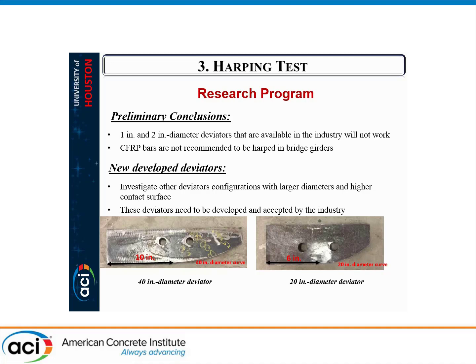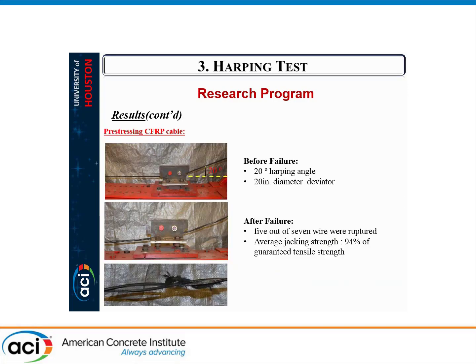So with the idea of increasing the contact surface and reducing the contact pressure, we developed two deviators. One of them has a 6-inch straight portion and a 20-inch diameter of the curve, and the other one had a 10-inch straight portion and a 40-inch diameter of the curve. And the result this time has improved a lot.